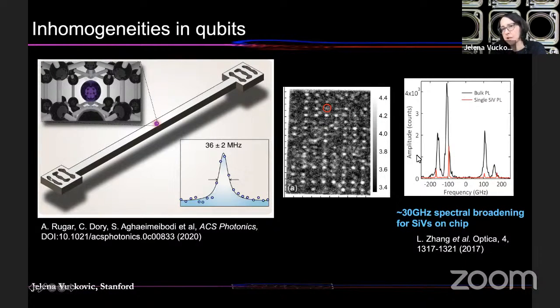This here is for the silicon vacancy, but the tin vacancy is very similar. These are transitions of the silicon vacancy, which are around 740 nanometers, and there are these 4 lines in the spectrum. When you measure a single silicon vacancy, you would see the red spectrum. Then when you measure an ensemble of silicon vacancies from exactly the same chip, you would see the black spectrum, which means there is some inhomogeneous broadening. We have measured 30 gigahertz of inhomogeneous broadening, which is much, much smaller than for indium arsenide or gallium arsenide quantum dots, where you have to deal with 50, 60 nanometers of inhomogeneous broadening. But still it's something that you have to resolve before you can scale systems up.